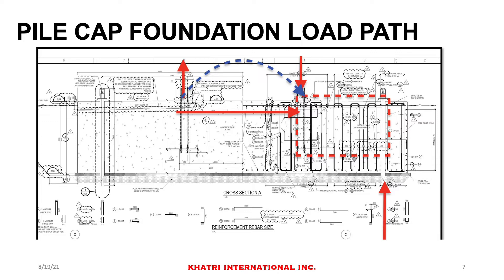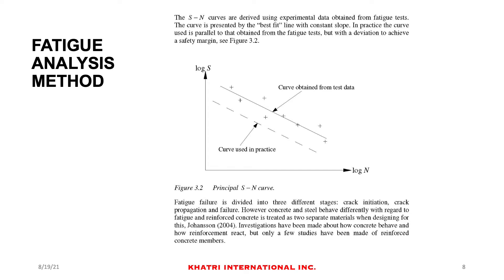The process is based on a lot of judgment, but also high-level analysis. We rely on the fatigue load spectrum given to us by the wind tower manufacturer. The fatigue analysis method uses the Palmgren-Miner rule, which is highly empirical — based on test data done in a lab for each type of stress situation. Based on those tests, we produce an S-N curve, where S is the stress on the vertical axis and N is the number of cycles to failure. We apply a factor of safety to that, using an actual design curve recessed back with a certain safety margin.